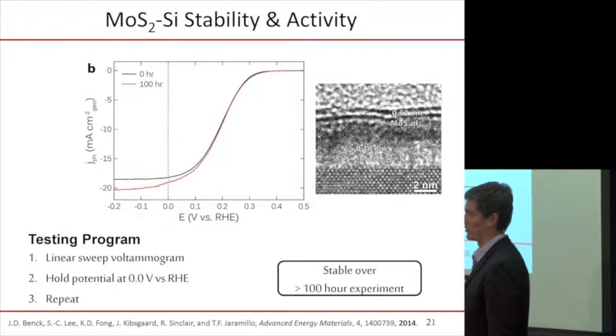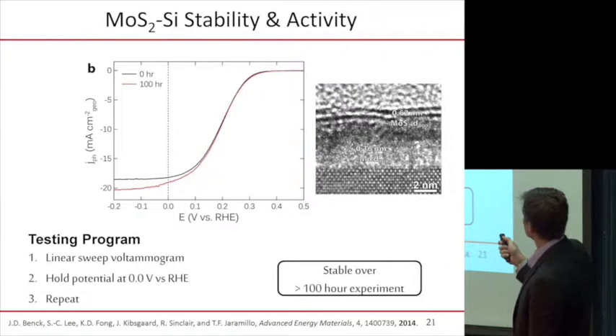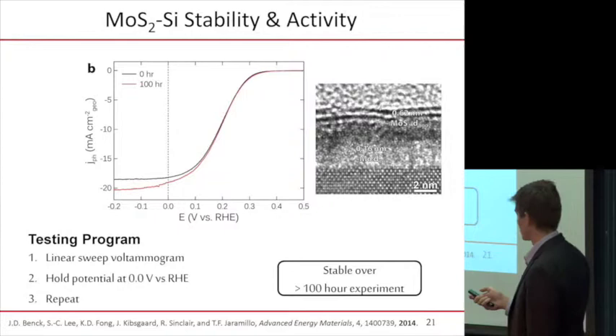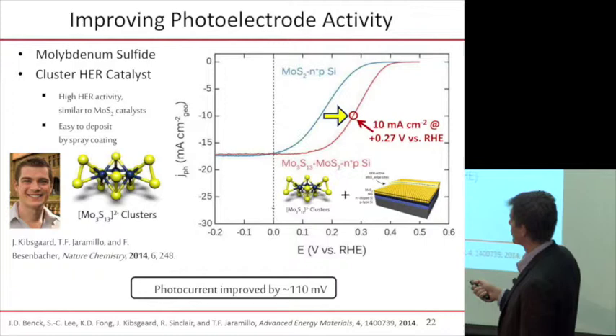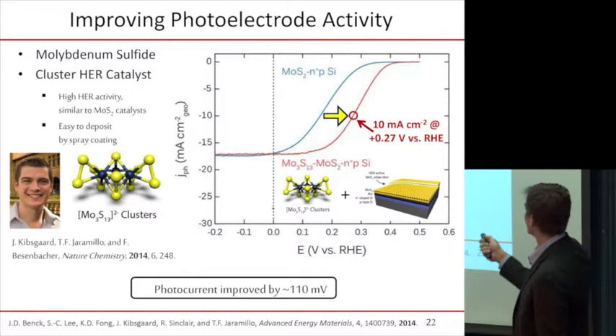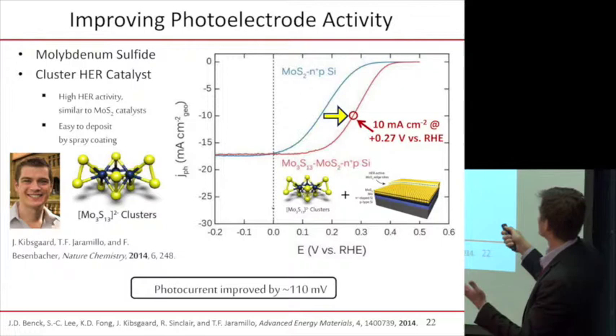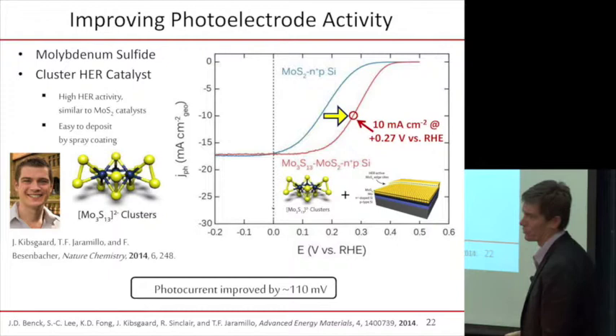It would die very rapidly without any protection. The only thing is that we noticed that there weren't a lot of edge sites on this surface. And as I mentioned earlier, the edge sites of this molysulfide is what's causing the catalysis. So then a postdoc in my group, Jakob, who had developed these Mo3S13 clusters, which have lots and lots of edge sites, he literally just spray painted them down onto the surface of this system I was showing you just now. And when you do that, you're able to move the current voltage curve even further to the right. Now we're getting these 10 milliamps per square centimeter at positive 0.27 volts versus zero.